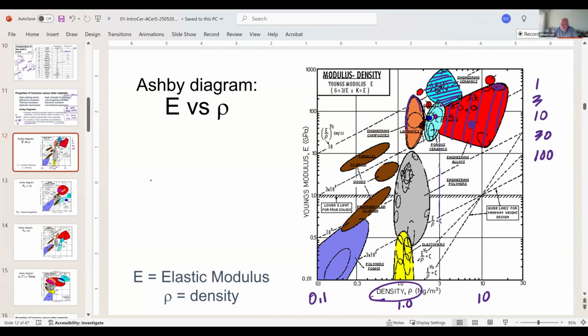I get into engineering composites over here. Here's my engineering composites, basically. And then the brown ones here are wood, but notice they have very low densities. And of course, if the density is below 1.0, then they float in water. And then you can have a highly oriented material. This is parallel to the grain. This is perpendicular to the grain. And you see that there is about an order of magnitude difference in stiffness if I am parallel to the grain or perpendicular to the grain.